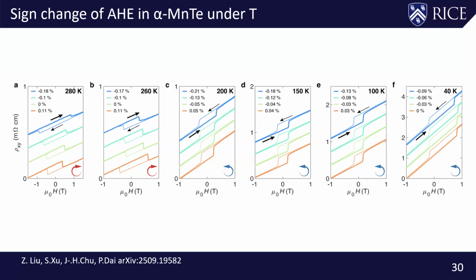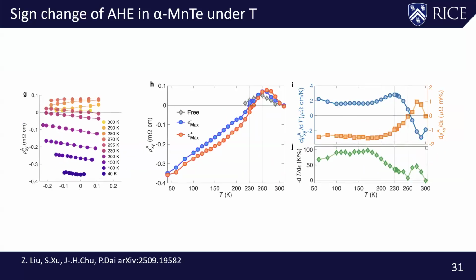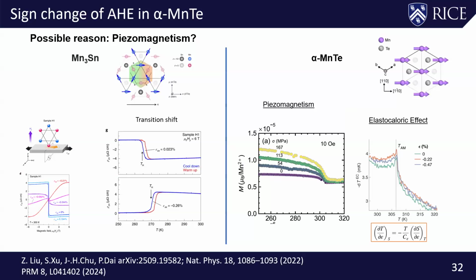The sample with twins and the bulk sample only show anomalous Hall roughly between below 300K to roughly 200K, and now we can see anomalous Hall all the way down to 30, 40 Kelvin. And this is the phase diagram that was mapped out, and as compared with the as-grown sample like this, now we can see anomalous Hall in a much bigger temperature range, basically indicating that all the domain boundaries have been eliminated. And we thought to compare this with the situation of anomalous Hall that's been seen in other magnetic systems. Let me try to argue why it's different.